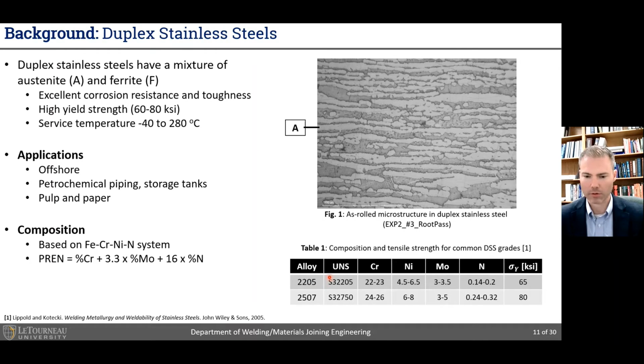Typical alloys, two common ones, are indicated here in this table, and you'll see that these are iron, chrome, nickel systems with a notable, intentional addition of nitrogen. So, of course, nickel is an austenite stabilizer, and nitrogen is intentionally added as well, and it also stabilizes austenite. The 2205 grade has 65 KSI minimum yield, and you can see the representative compositions here. The so-called super duplex 2507 goes to higher yield strength as well as improved corrosion resistance due to the additional degree of chromium, nickel, and moly, as well as nitrogen.